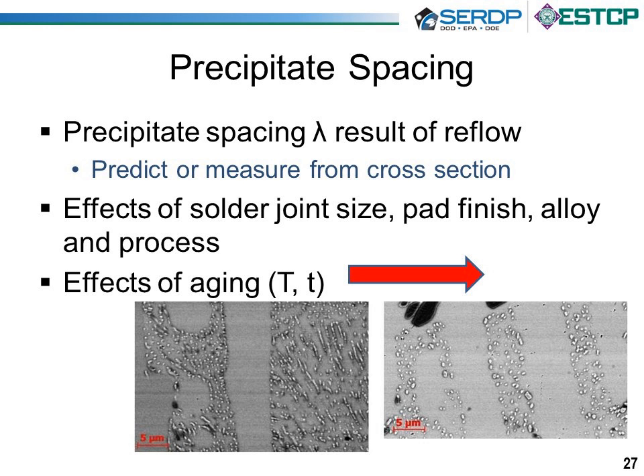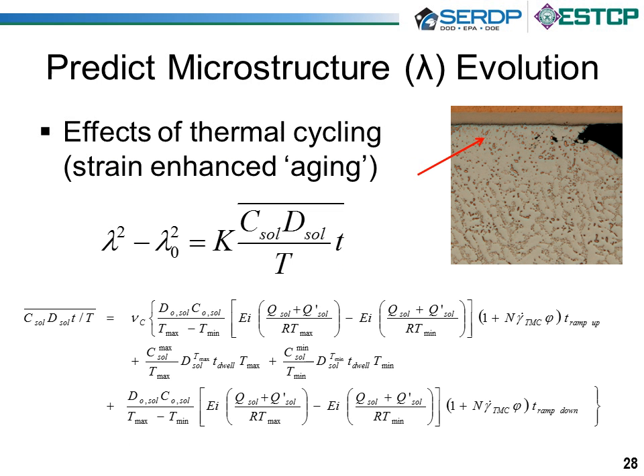It varies with the size of the joint, with pad finishes, with alloys and processes. But more importantly, as you can see there also, we took a particular case of a material and we heated it for a while, not very high temperature, but for a while, and these precipitate distributions changed enormously. Okay, so that is part of that lack of stability. And the other thing that happens, aside from heating it, is if you do cycling, you're putting stresses on and temperature, and in that case, you're also changing the precipitate distributions, and they're changing differently in different parts of your joint because the stresses are different there.